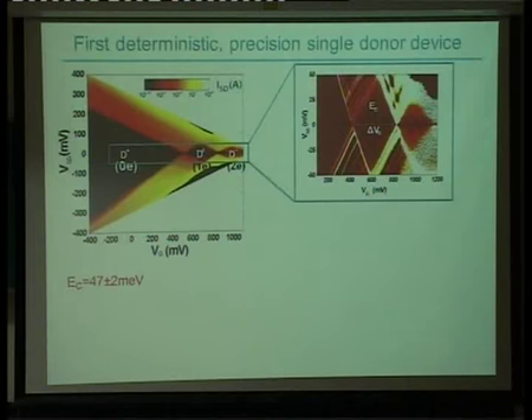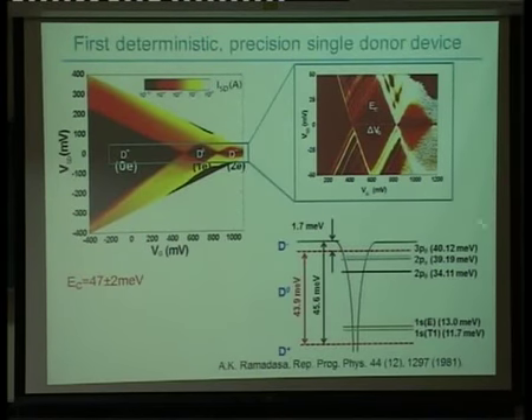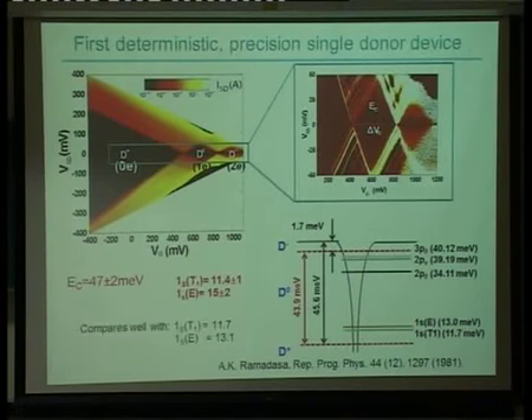And if you cool that down to millikelvin temperatures, you can actually measure the charging energy here. And the key thing about the charging energy is exactly what you would expect if you look at optical spectroscopy measurements of a single phosphorus donor in bulk silicon. So here you see that the transition is about 43.9 meV, and here what we're measuring is about 47 plus or minus 2 meV.